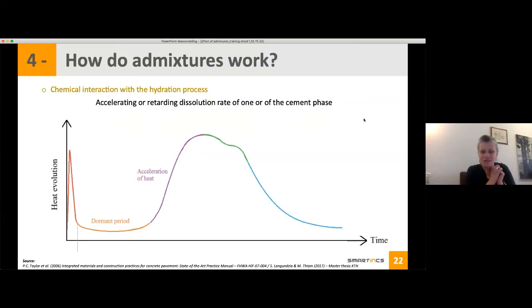So now, how do admixtures work? There are different ways that you can work, but I've just shown the hydration of the cement, and then you can say, if I want to increase or decrease the setting time, then I have to play with a chemical reaction. So an admixture can accelerate or retard one of the phases. You can see with the dormant period, you can shorten this dormant period, or you can extend it.